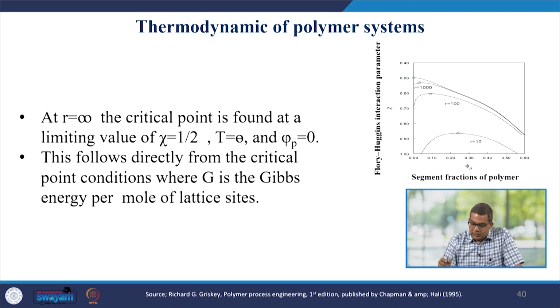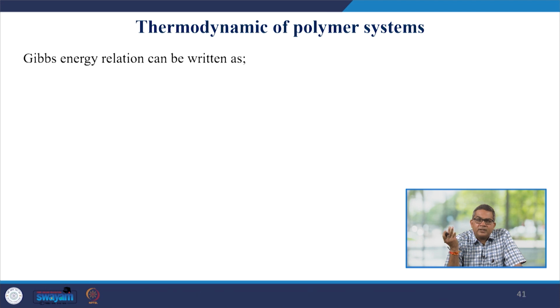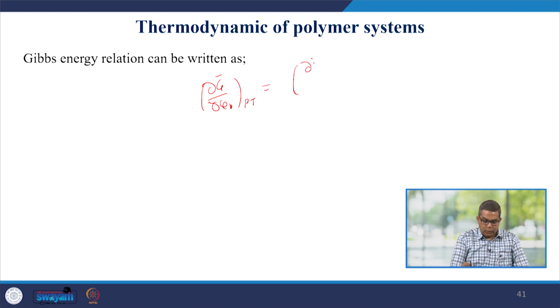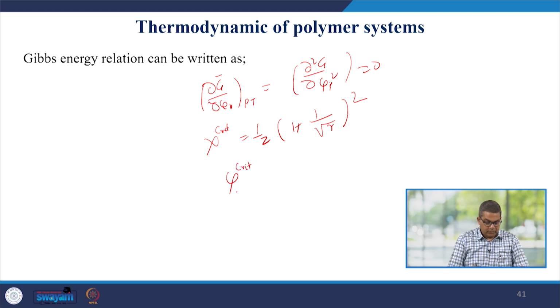Now, at R infinity, the critical point is found at the limiting value of chi equal to half, and T is equal to theta and psi p is equal to 0. Now, this follows directly from the critical point condition, where G is the Gibbs free energy per mole of lattice site. This Gibbs energy relation can be written as del G over del psi p at constant pressure and temperature, del 2G over del psi p2 is equal to 0, which leads to this critical chi equal to half into 1 plus 1 over square root of R whole square, and psi critical at given pressure is equal to 1 over 1 plus square root of R.